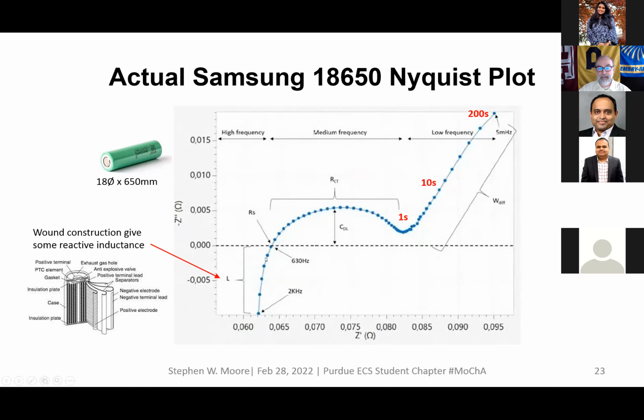You'll see a little bit of inductance, but then the capacitance takes over, and with the Samsung at 630 hertz, meaning any pulse you apply to the cell that's slower than 630 hertz, which is about 0.002 seconds, it's going to act capacitively. It's going to have capacitive reactive impedance. And then after about 1 second, it's going to start going up the Warburg tail, 10 seconds. And you see up here at 5 millihertz, which is 200 seconds, is way up here on the Warburg tail. And so this right here is the actual real life impedance of the Samsung cell.